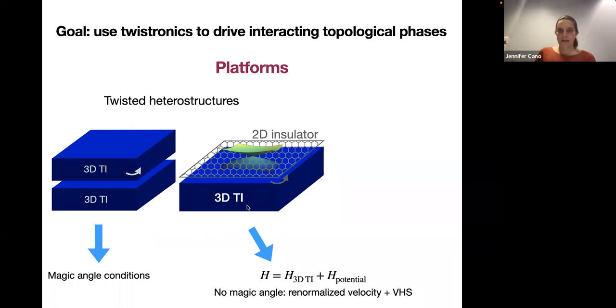The bottom line here is that the effect of making some heterostructure like this is that the 2D insulator, if this is an insulating material, will impose a potential on the TI surface. If these two materials are very closely matched but mismatched, this will create our moire pattern, and this potential will be some slowly varying potential on the TI surface. The basic result that we find is that this setup doesn't realize a magic angle, but it has two main effects that I'll talk about: it renormalizes the velocity of the Dirac cone, and it also introduces a Van Hove singularity that can drive magnetic surface states, which is what we're after.